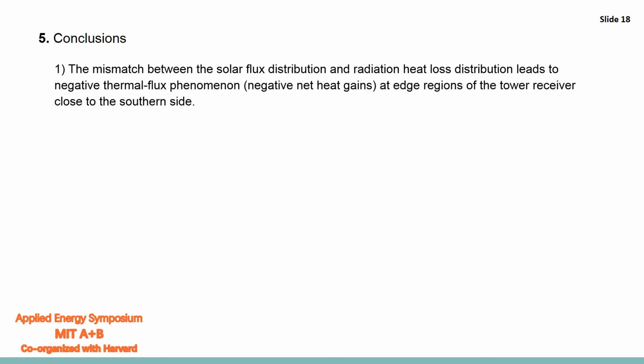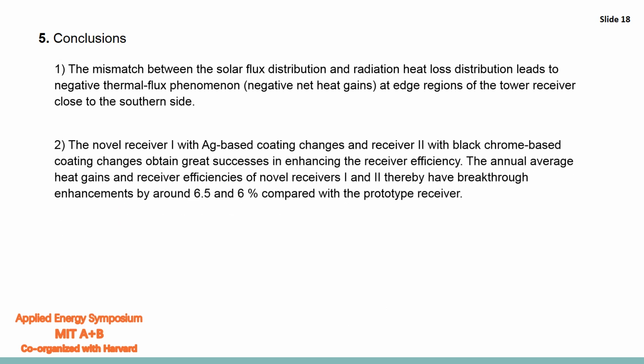The first is that the mismatch between the solar flux and the radiation heat loss distribution leads to a negative thermal flux phenomenon at regions of the tower receiver close to the southern side. The novel receiver 1 with silver-based coating and the receiver 2 with black chrome-based coating obtained great success in enhancing the receiver efficiency. The annual average heat gains and receiver efficiencies of novel receivers 1 and 2 thereby have breakthrough enhancements by around 6.5 and 6% compared with the prototype